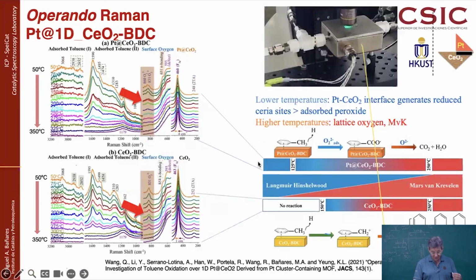And well, basically that was telling you how important it is. The reduction of cerium is fostering not only random defects here and there on cerium, but because of the interface you have more line defects, and these line defects allow peroxide binding on these two sites. It results in a more efficient activation of the peroxide than when it is on a single site.